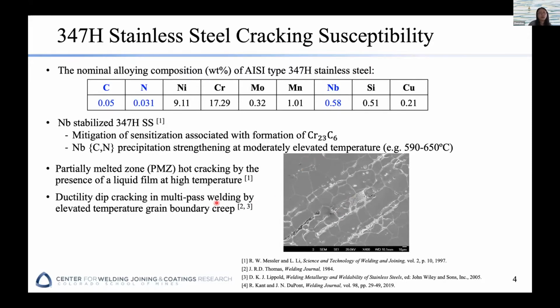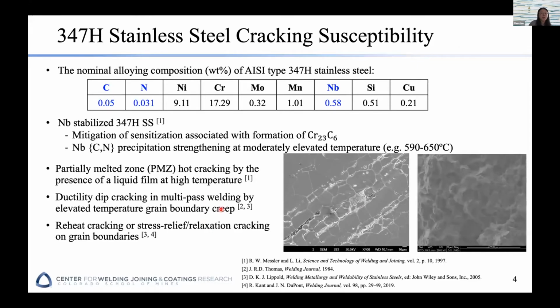Another mechanism in this material for cracking is ductility dip cracking, which is related to grain boundary creep, accumulation of strain into the regions near the grain boundaries and causing earlier cracking. And this image here shows a typical fracture surface. You can see the grain morphology, so that means it's cracking along the grain boundaries. Today we're going to focus on the cracking mechanism called reheat cracking or stress relaxation cracking.